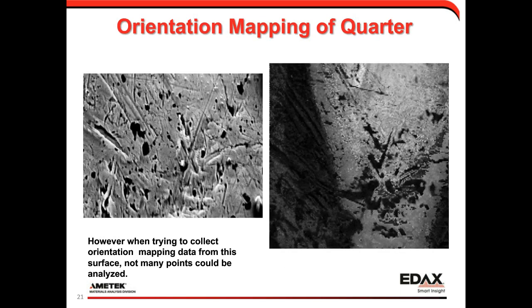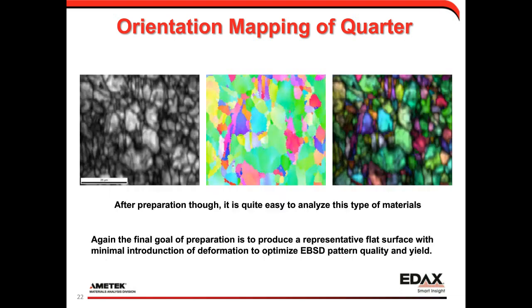So this is a map from a section of a quarter. We see the SEM image on the left and the EBSD image quality map on the right. When I show you the points that we can index, you see there are very few of them that we actually index with high reliability. So without preparation, we can sometimes get patterns, but we don't get reliable mapping. But if we take that same material and polish it, then with our EBSD results we see grain contrast, we see orientation contrast, and we get a representative view of the microstructure rather than just a few patterns here or there.